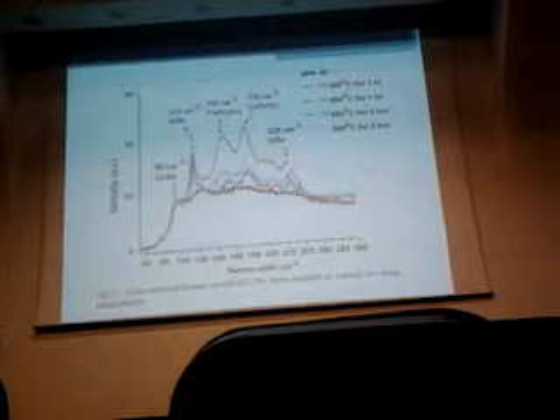Similarly, we have also drawn the Raman spectrum of the cross section of the prepared sample. The peak at 152 per cm corresponding to copper indium 3 selenium 5 goes on increasing as the annealing temperature increases.